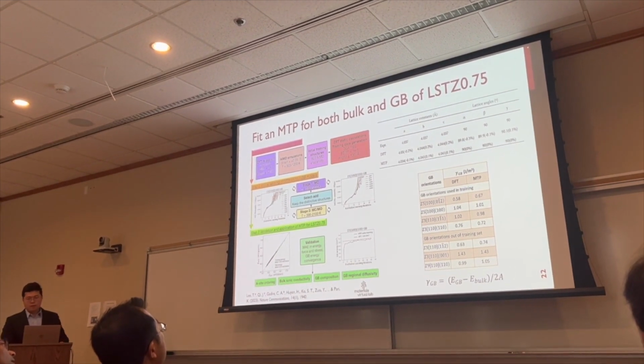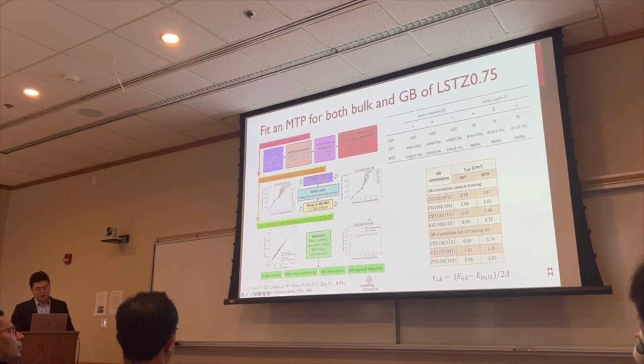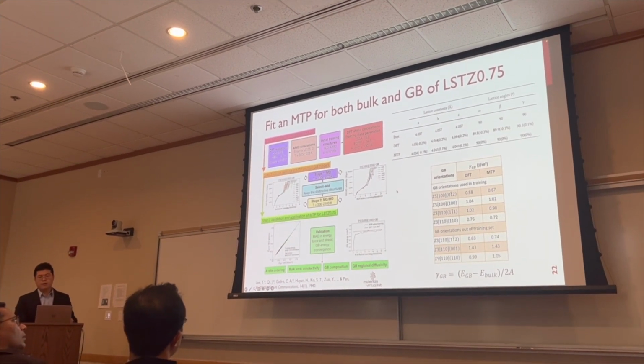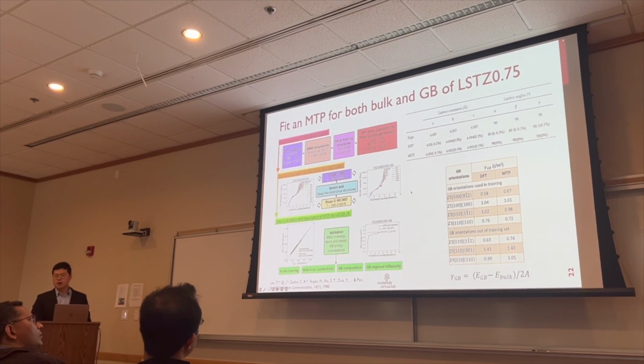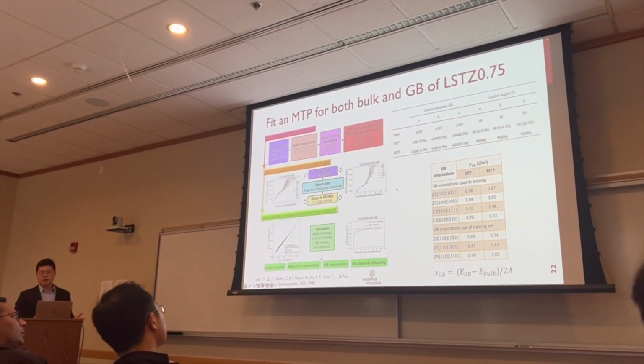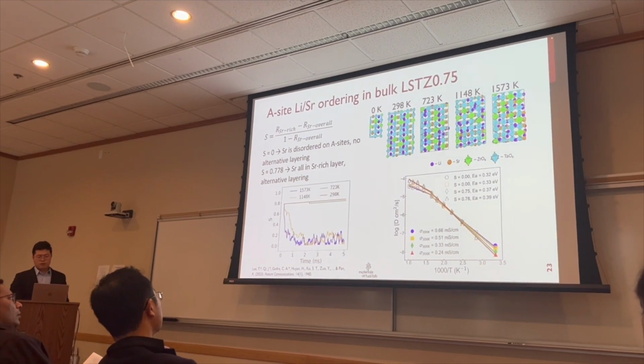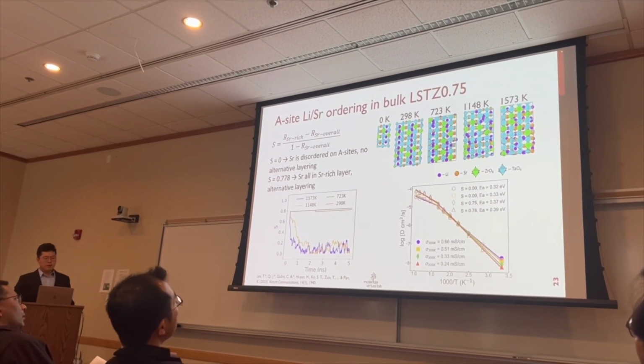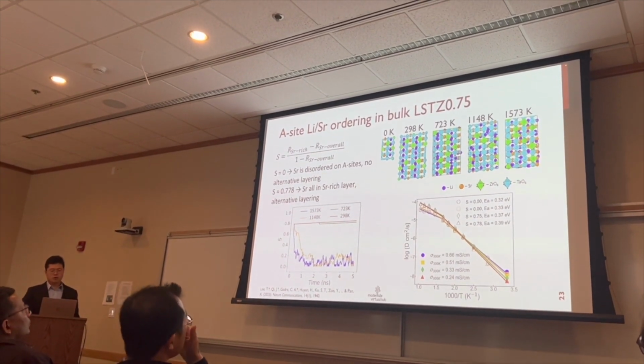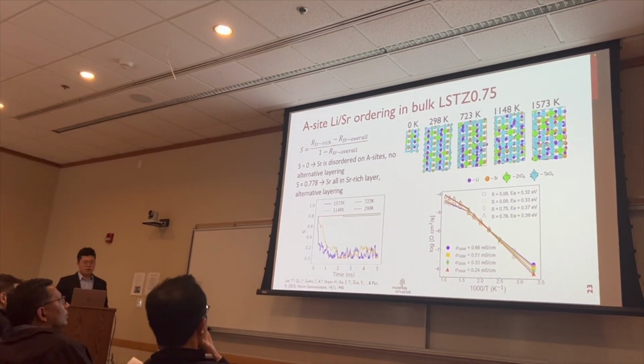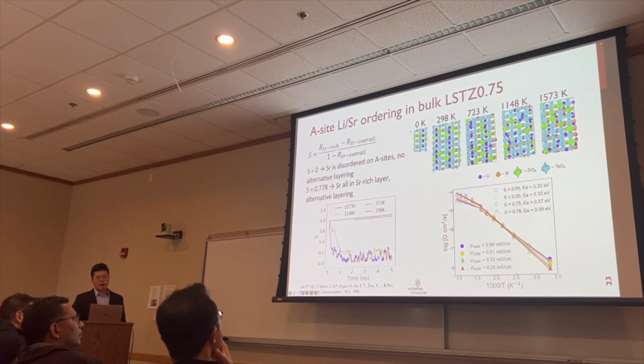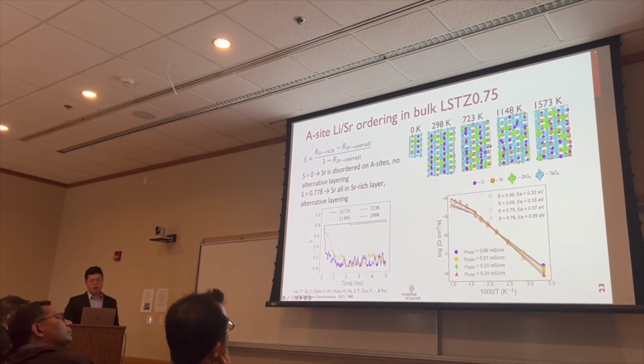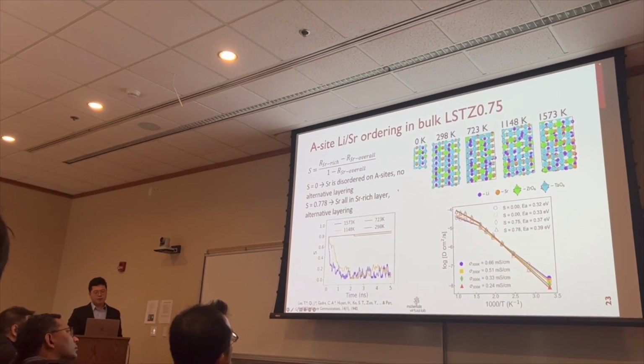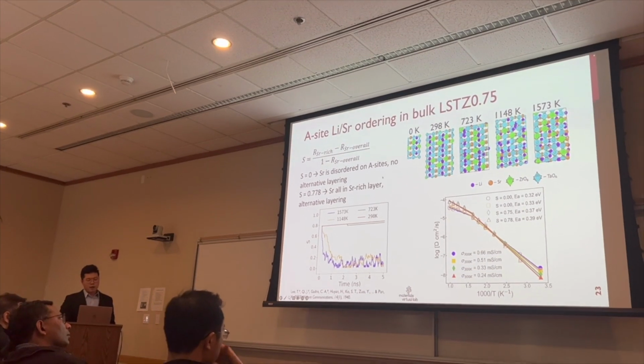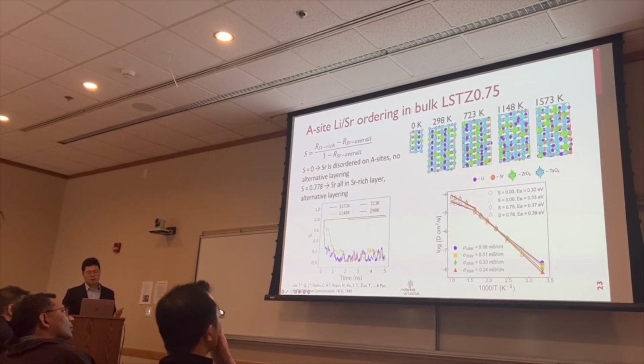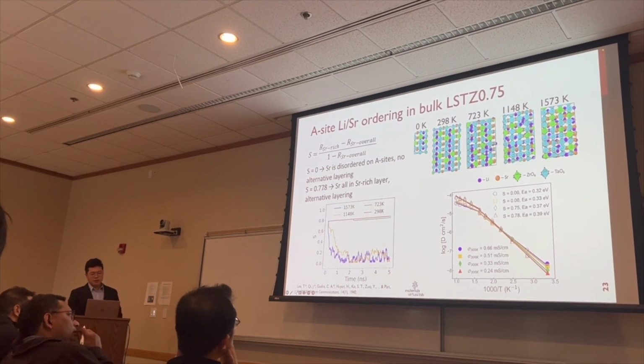Okay. So let me continue. I want to show here that with MTP, we can effectively collect some grain boundary structures, and we are now confident to apply this to some larger scale simulations. So the first scenario we apply it to is to study the A-site lithium-strontium ordering in the bulk structure of LSTZ 0.75. In this case, at 0 Kelvin, the lowest energy structure has the alternate stacking of lithium and strontium on the A site. This corresponds to an ordering parameter equal to 0.778.